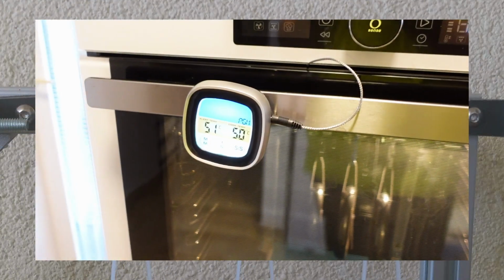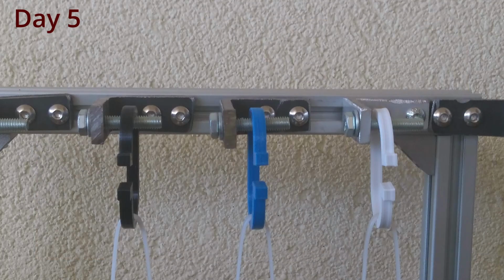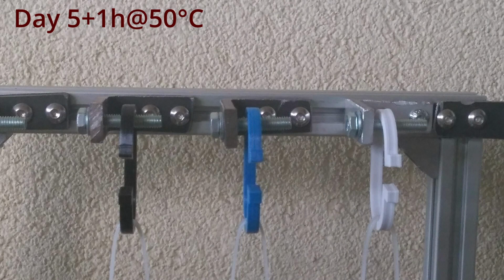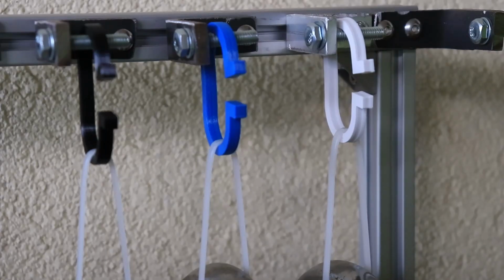and then I place the test objects in the oven for 1 hour at 50 degrees Celsius. So this was day 5, and this was after 50 degrees Celsius heating. And now removing of the load.